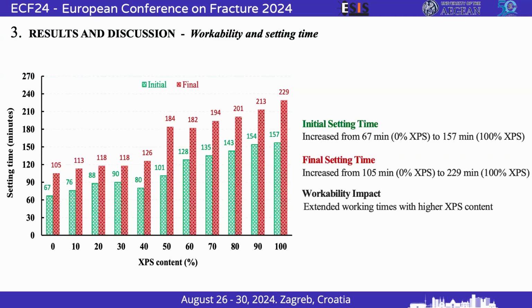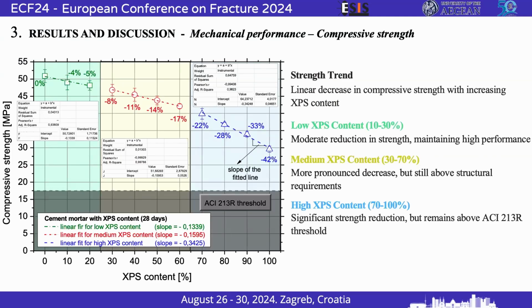Moving to the results, with regards to the workability, so workability is how the material flows, if it's easy to manipulate it in the fresh state, we have seen that the incorporation of the XPS actually improves the workability, so it makes it a little bit more flowable, and this is preferable in some applications. Also, we have seen that its use increases a little bit the initial setting time and the final setting time. So it takes the material a little bit longer to harden, which is also, in some applications, something we actually want.